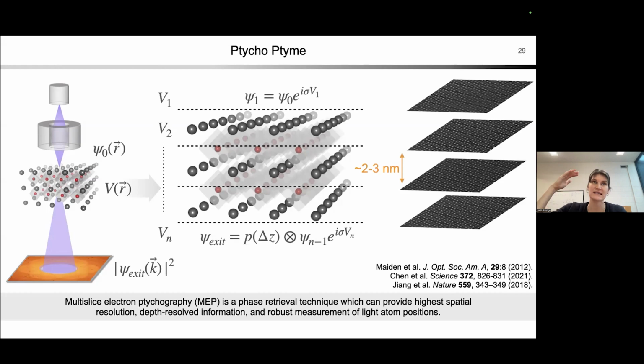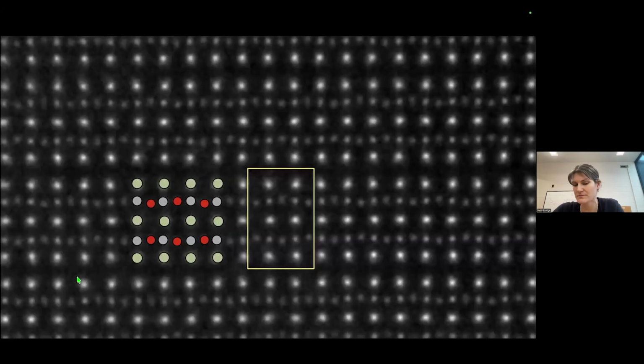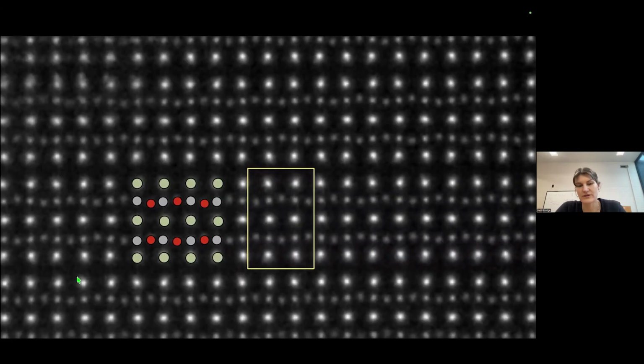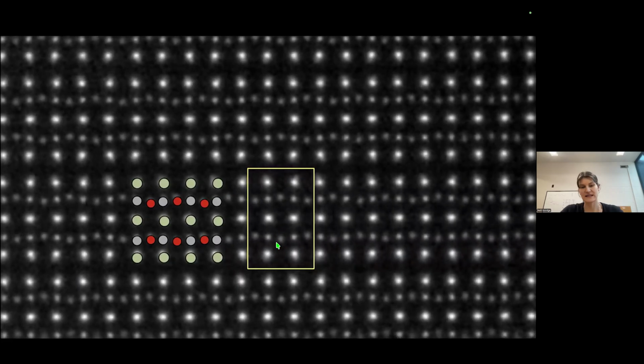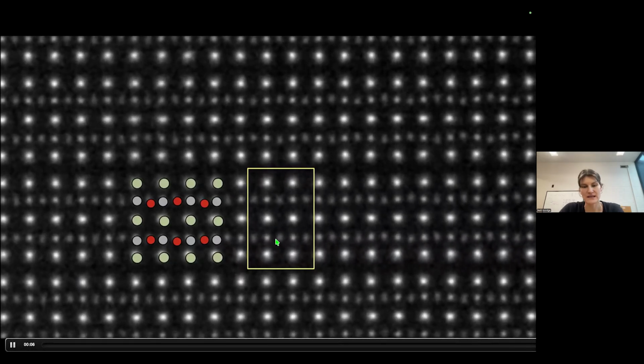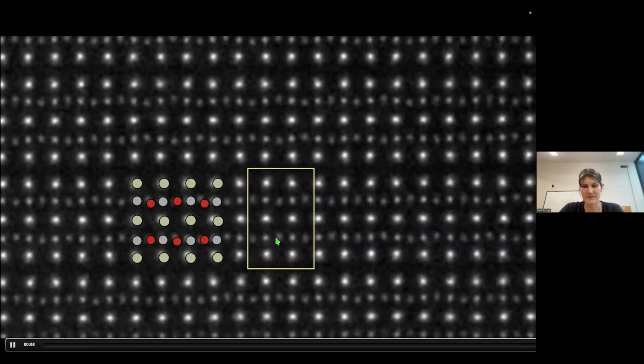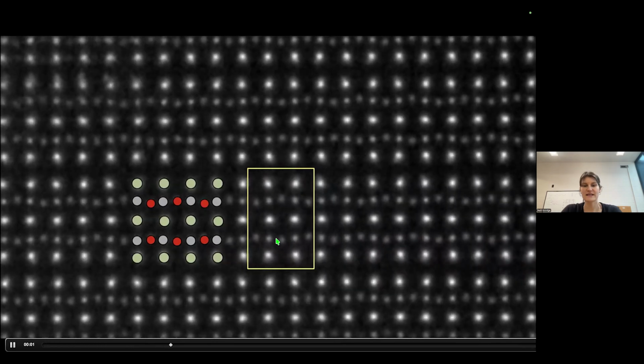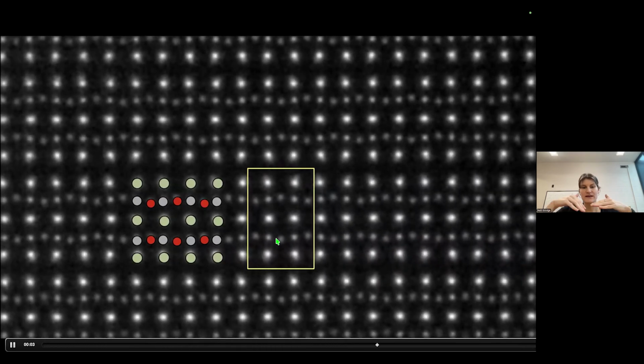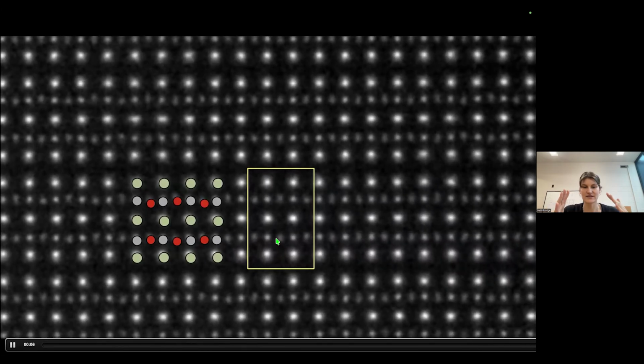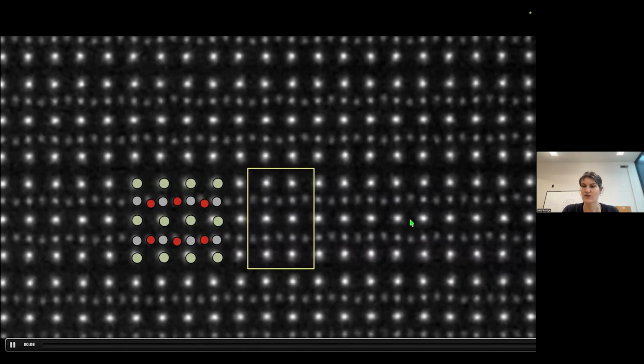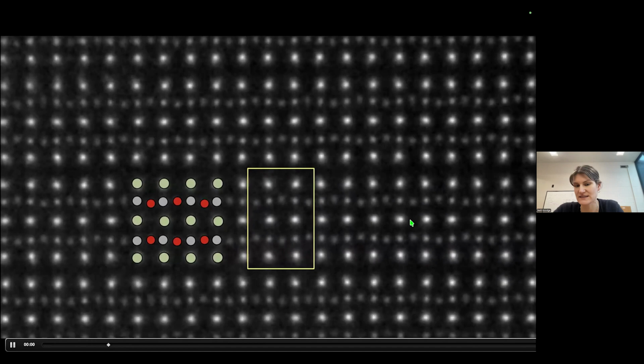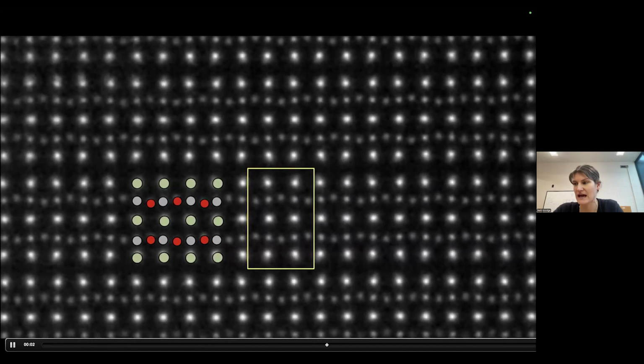And so we can see not just one projection of the sample, but we can actually start to differentiate some of those slices with a spatial resolution of a couple nanometers. This is a ptychographic reconstruction that Lopa has done as we cut through the depth of the sample. Here you see these oxygen atoms. My cursor maybe came back, but you can see very clearly, as it goes deeper through the sample, how the oxygen columns even swap in the crystal, right? So this is an unprecedented level of access to these atomic structures that we haven't really had in the past.